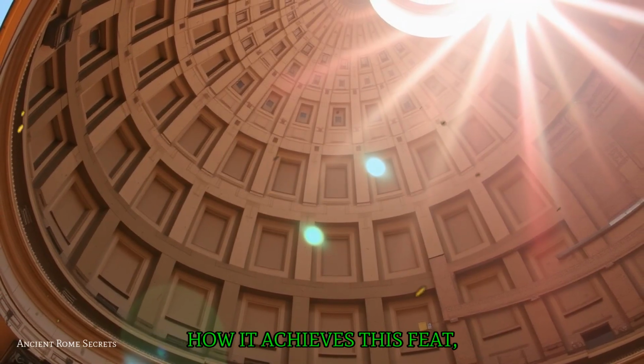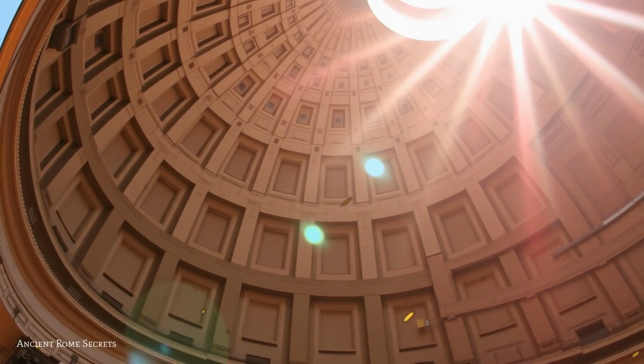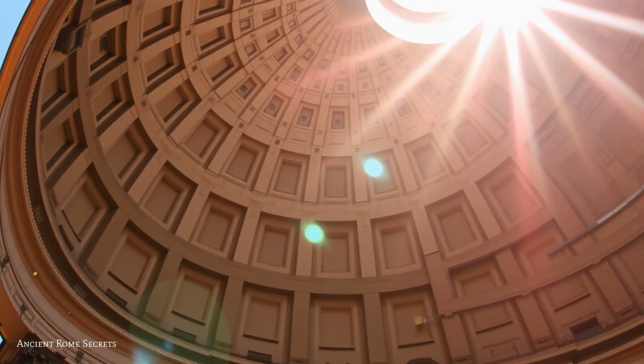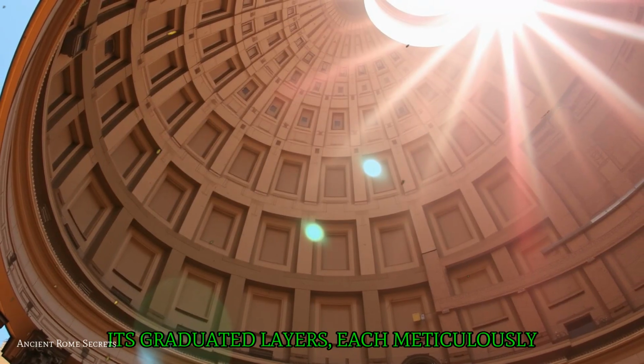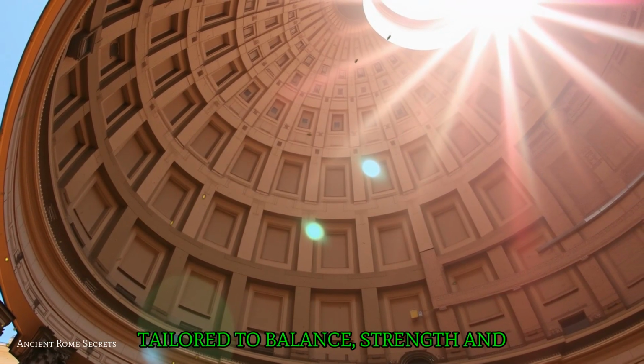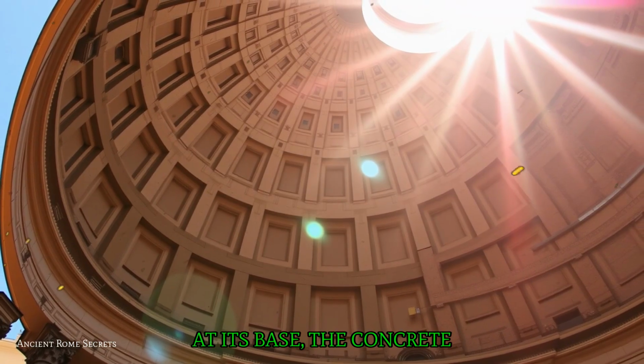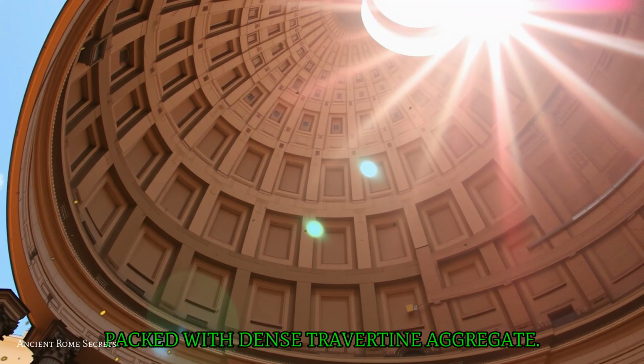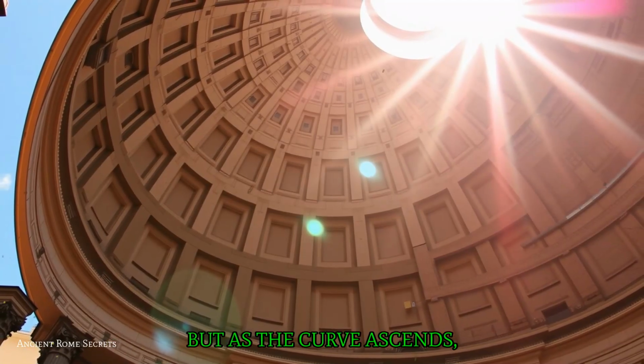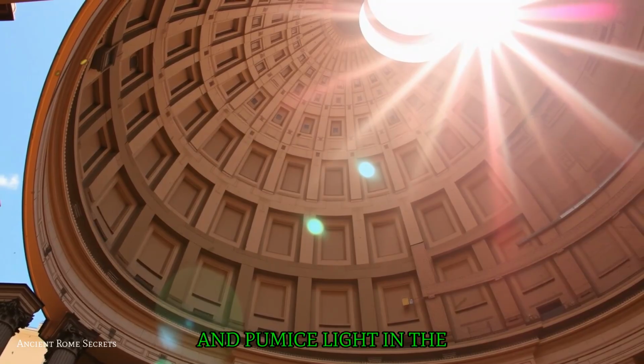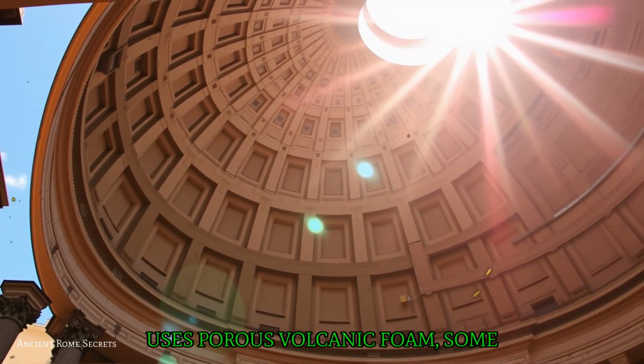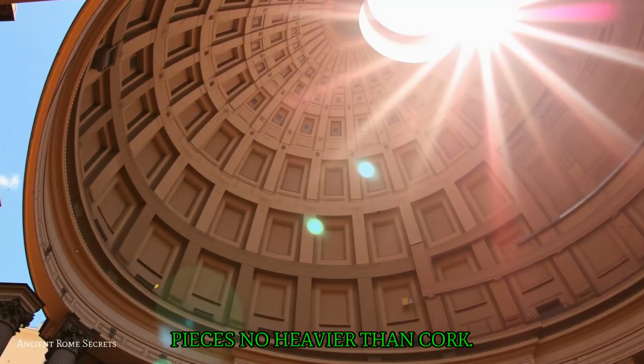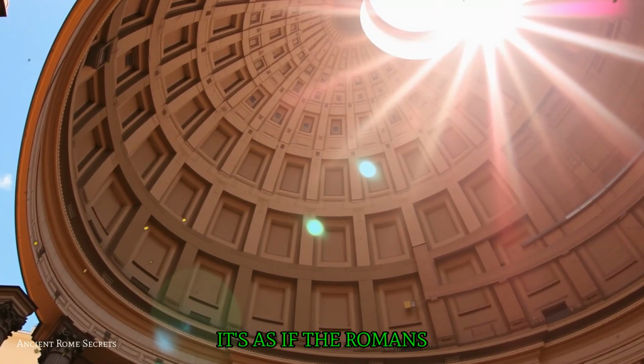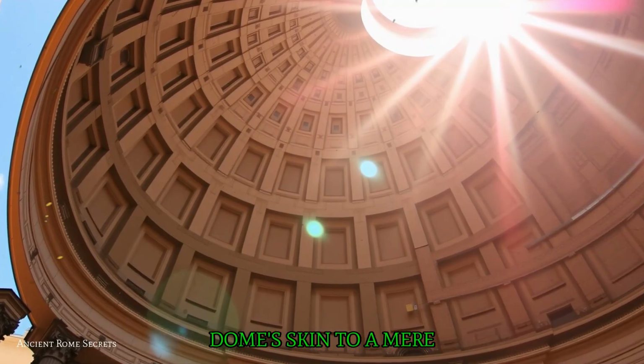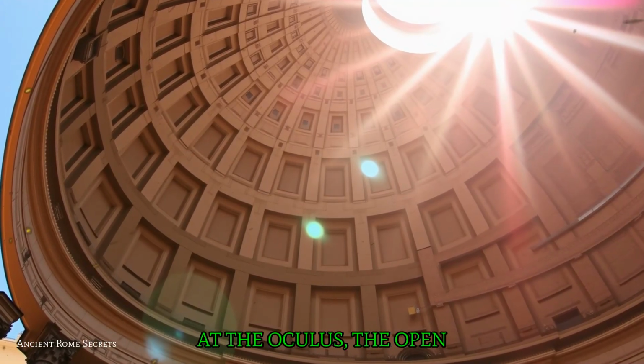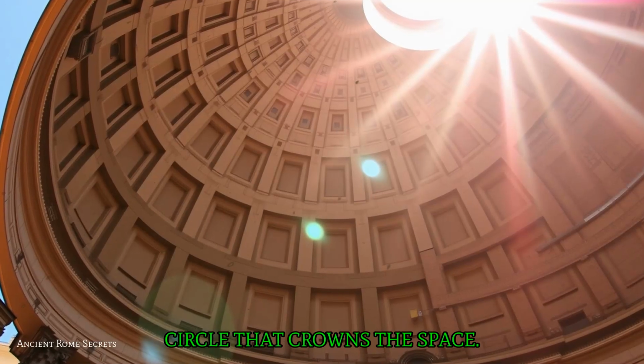What's even more astonishing is how it achieves this feat, not through brute thickness, but through ingenious design and material alchemy. The dome's secret lies in its graduated layers, each meticulously tailored to balance strength and weight. At its base, the concrete is nearly 6 meters thick, packed with dense travertine aggregate, but as the curve ascends, the mix transforms. Volcanic tuff and pumice lighten the load, while the very top uses porous volcanic foam, some pieces no heavier than cork. It's as if the Romans sculpted gravity itself, thinning the dome's skin to a mere 1.5 meters at the oculus, the open circle that crowns the space.